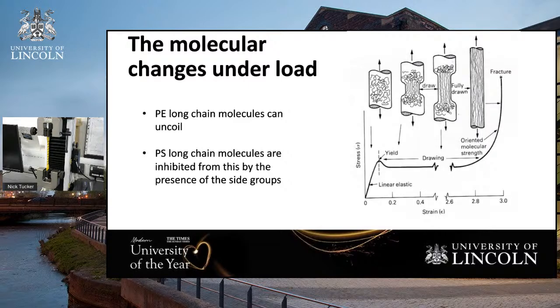We are giving our polythene sample the coiled up, low energy state, long chain molecules are having the chance to uncoil and stretch out. And that's what's happening during the drawing process that I'm showing on my little graph here. So we'll leave that one go. If you can see the graph, you can see the extension in millimeters is going up, but the load is stuck at about 400. So under that load, it just continues to stretch.